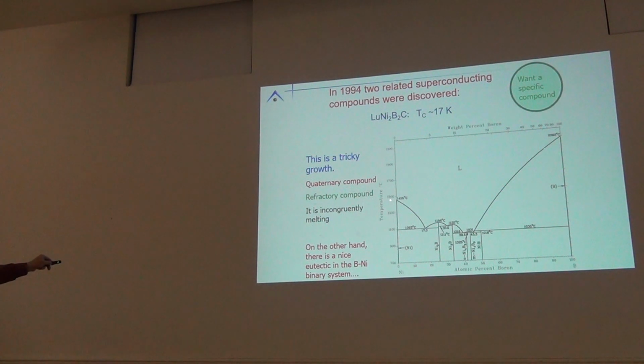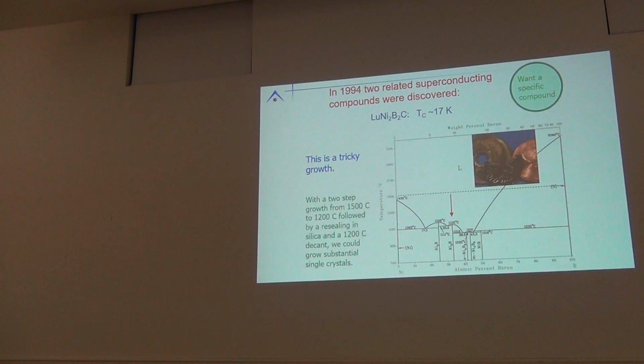interesting. So what you can do is you can look at the nickel-boron phase diagram, and remember, we're growing out of liquids, and you have this cascade of eutectics. We have eutectics as low as about 1,000, okay? The nice thing is this means that we have a region that we can grow materials out of. What we were able to do is come up with this 2-step process where we could cool the 1221 and nickel-boron flux from 1,500 down to 1,200, and then reseal into silica and decant, and you can get lovely, nice crystals, and with lovely, nice crystals, you can do physics, okay?